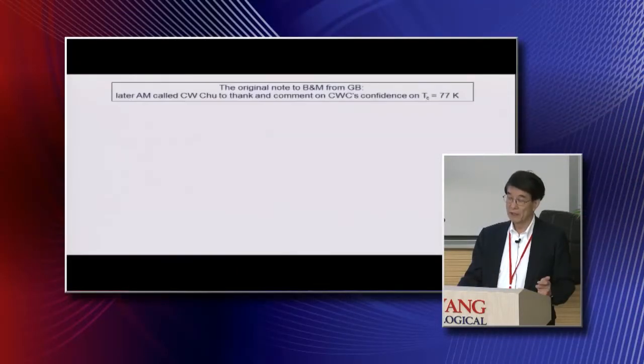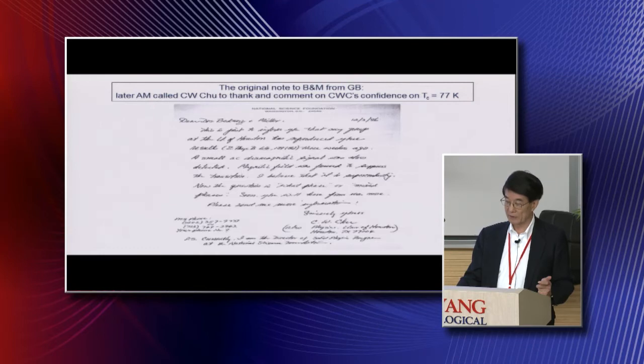So very quickly, we confirmed their results in late November, and we obtained more. Once we reproduced their results, in fact, I dropped Alex Müller and George Bednorz a note on December the 3rd, telling them we reproduced their results and we believe the temperature will continue to go up. And Alex Müller actually called me up to thank me, because at that time, there was lots of pressure on them, whether that's true or not. And they also commented later that they couldn't believe I was so optimistic, because at that time I felt TC should go up to 77 degrees for sure.